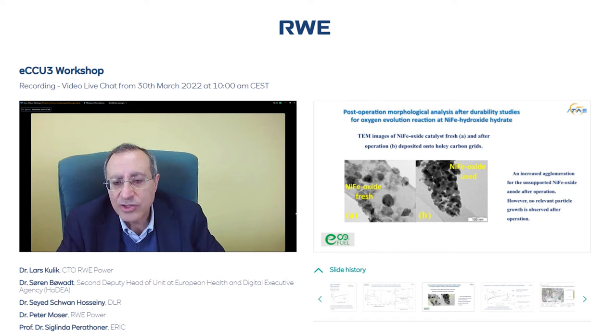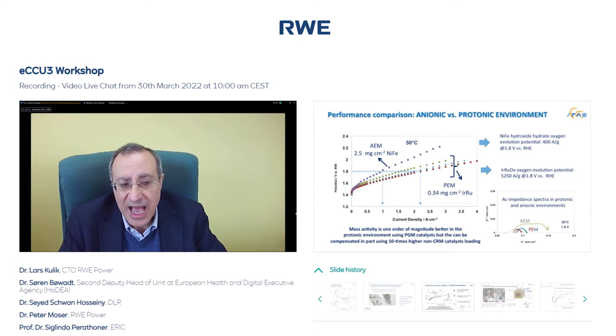So we can also see that we have a small particle size after 1,000 hours operation. This is in slide number 13. And of course, there is some gluing effect by the ionomer, but still the particle size is sufficiently small. And now we can move to slide number 14.